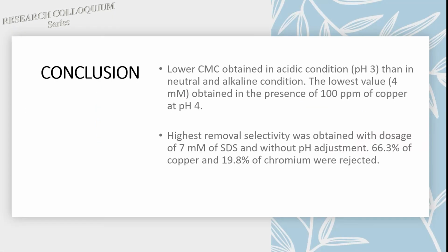So lastly, this is my conclusions. We do found that the lower CMC obtained in these acidic conditions, which is at pH 3, than in the neutral state and in the alkaline conditions. The lowest value of this CMC could be obtained in the presence of 100 ppm of copper at pH 4. Highest removal selectivity was obtained with the dosage of 7 millimolar of SDS and without any pH adjustment, which the rejections could be obtained with is around 66 of copper and also about 20% of chromium.